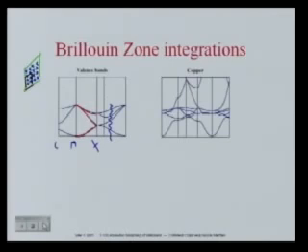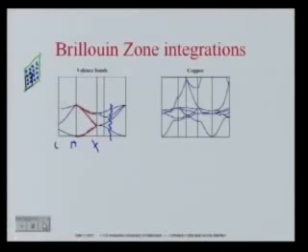So that also means that, say, if 64 k points is a good number for a regular unit cell of 2 atoms of silicon, if now you are going to use a unit cell that has maybe 128 atoms, much larger, to calculate a vacancy formation energy, you really need only 1 k point to calculate your total energy with the same accuracy. So there is this general idea of scaling and folding. You make your real space calculation larger, you actually need to use fewer k points.